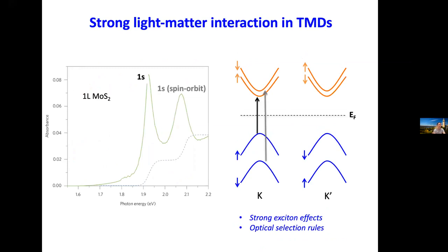Monolayer TMDs interact with light very strongly. The optical response is dominated by exciton resonances. This is about 10-year-old data — if you look at the fundamental exciton, the absorption can be as high as about 10%. As we'll see later, this makes optics a very sensitive probe of the system. There are also interesting optical selection rules that couple circularly polarized light of different handedness exclusively to specific spin-valley degrees of freedom.